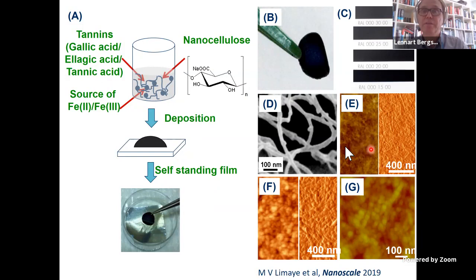This is also visible with AFM, where you go from the pure film to the film coated only with tannins, like gallic acid. You form small clusters, then react it with iron, and the clusters or nanoparticles reside on the surface of the fibrils.